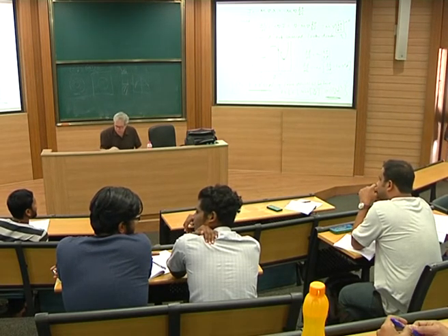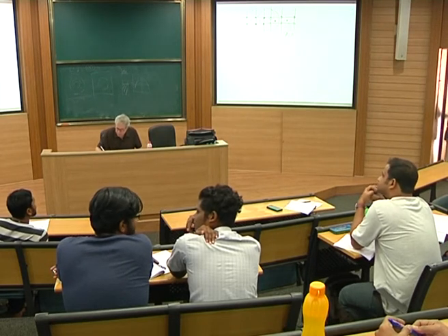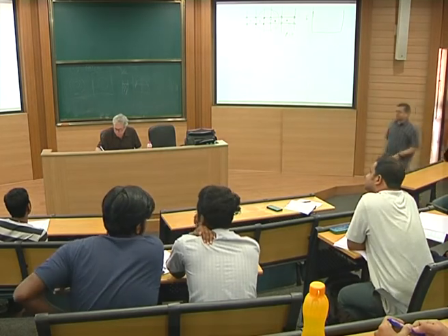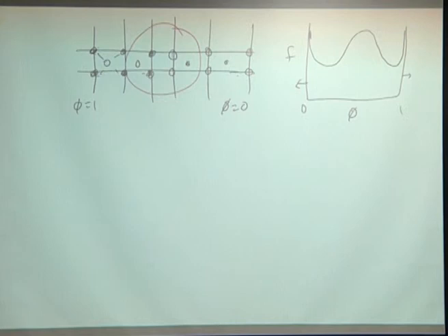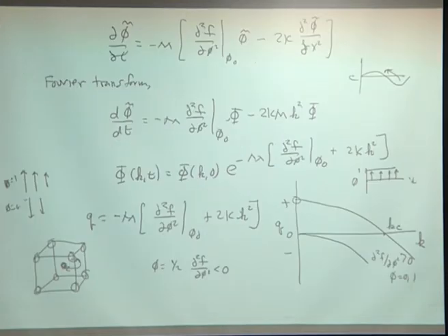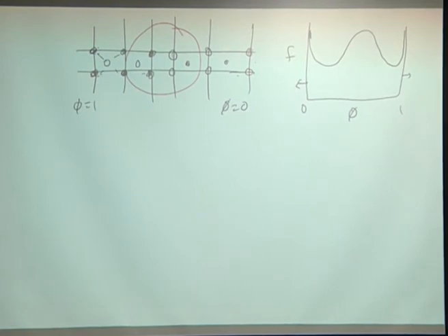I want to emphasize that, because if you look at the real free energies in the system, the real free energies look like this. And over here, the slopes go to infinity, so it's impossible to get an order parameter less than 0 or greater than 1. Whereas here, it's like a Taylor expansion, a Landau expansion, so sometimes you can leak out over the other sides. The reason people don't use these regular solution type models is that it's x log x, right? So you have this complicated thing you integrate. You can't do it analytically, and it's hard to figure out.